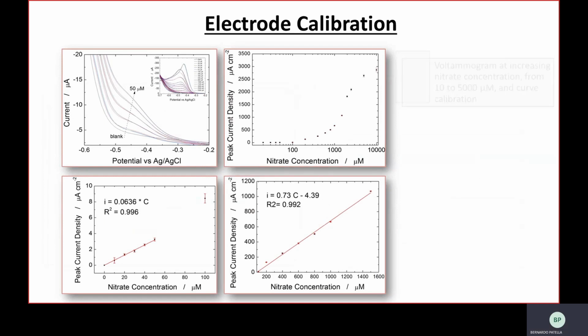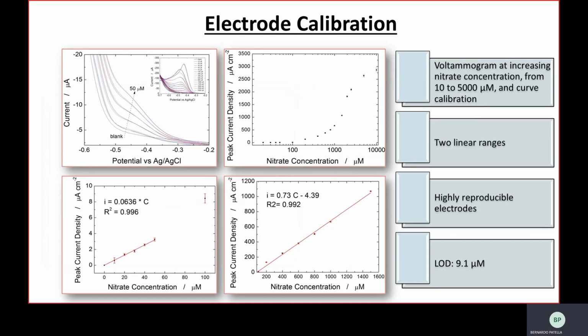Using all the optimized conditions, the electrode was put in contact with different amounts of nitrate ions, and the signal intensity increases from 10 micromolar to 1.5 millimolar. Particularly, two linear ranges were found as shown, and a limit of detection of 9.1 micromolar with a standard deviation of 5% was found. This is an important result because this limit of detection is almost 1,000 times lower than the limit set by the Environmental Protection Agency.